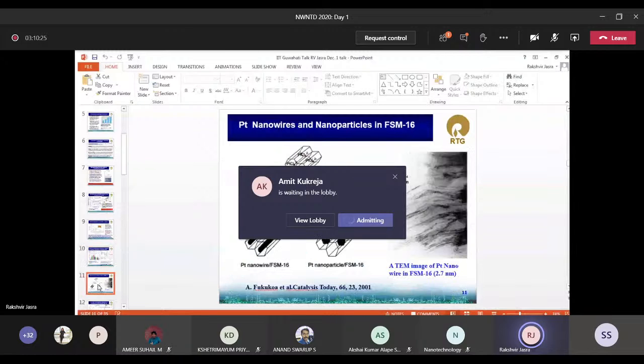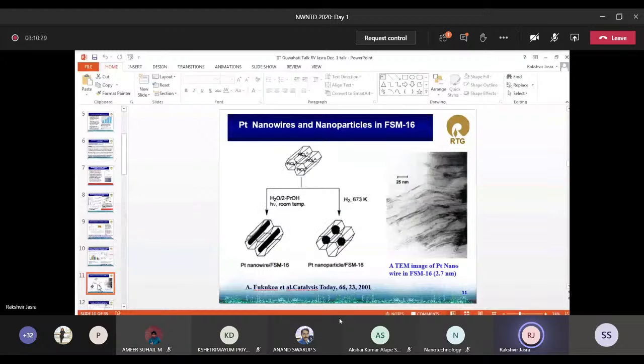The second point which has also been realized when we talk about nano metal particles is that the shape of the nanoparticle also influences the activity significantly. Now here they have made platinum nanowire inside a porous material, FSM-16. This is something equivalent to MCM-41 silica, which is an ordered mesoporous silica.